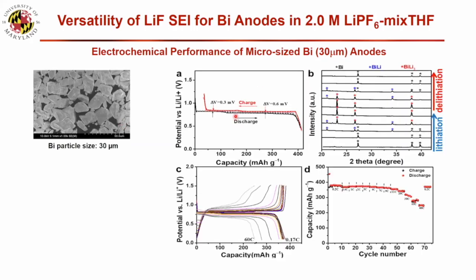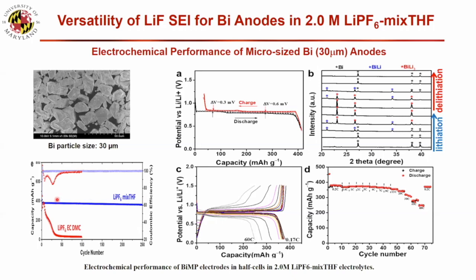And we just charge-discharge. This is the charge-discharge curve and rate performance, because this is an electronic conductor. So the rate is even high, the C rate even high, and the cycle life. So we demonstrate this is a universal design. And then we check the full cell.